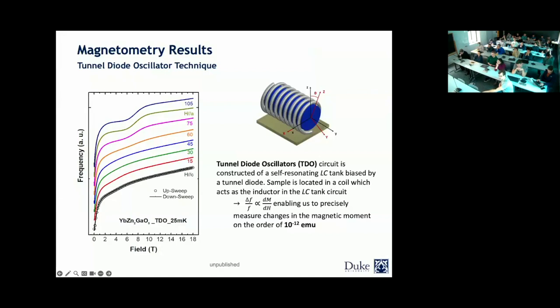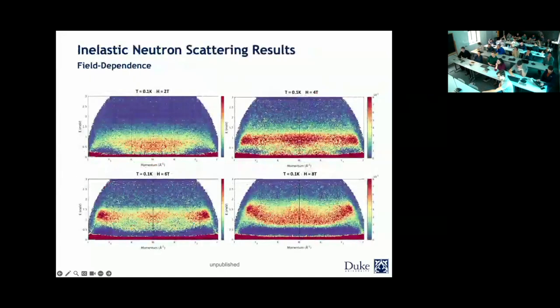We are still not quite sure what exactly is happening here, but we looked at inelastic neutron experiments. Here you're looking at the energy as a function of momentum at different fields. You can see there is a continuum of excitations, but if you look at 4 Tesla, it starts to show 2 different bands. There are excitations appearing at the K points at lower energy, and then a band up here. Here you're looking again at these 2 different bands at 8 Tesla. That shows a much nicer dispersion compared to the 1114 compound.